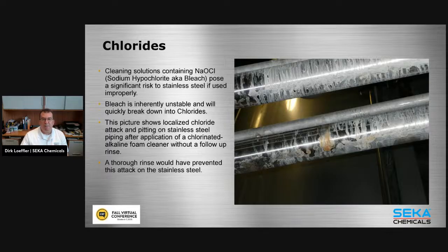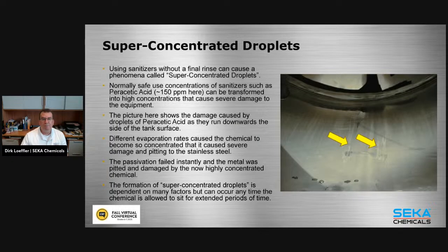Just kind of how chlorides can be affecting our pipes. So this was actually a company, a brewery in the Northeast. After an extended shutdown, they brought in a contractor and had all their pipes cleaned with a chlorinated alkaline foam cleaner. Well, the contractor unfortunately forgot to rinse the pipes down, destroying about $300,000 worth of process piping in the process. They had to essentially rip all this piping out, do all the piping over before they could start up again, adding another extensive bill to their already extensive shutdown bill.